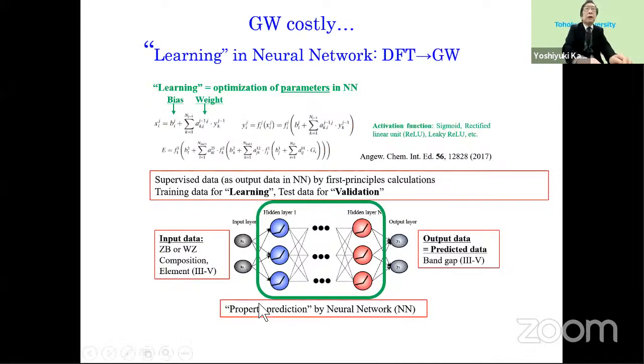So we worked, but GW for this system is too time consuming for us. So Mizuseki worked on learning, meaning neural network learning from DFT to GW. We take data from experiment of the band gap, and those are used as teacher data, and then we compute many DFT calculations and fit to the GW result or the experiment. And then we prepare a lot of data computed by DFT, but with the band gap modified by this neural network knowledge. And then this is backward prediction.